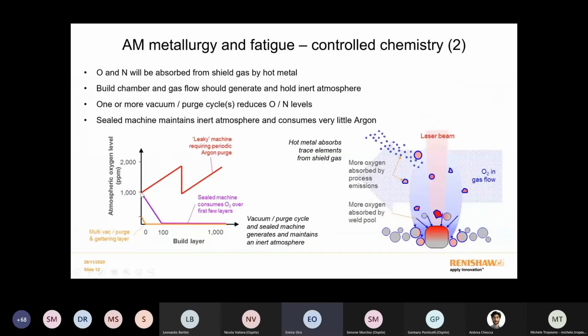Okay. This behavior, this red line, is a machine that is not behaving properly, so it continues to leak argon, and you have to purge the machine regularly, and you still have an unwanted concentration of oxygen inside the inner chamber. This behavior is a good machine: once you have an initial purge phase, and then maybe in the first 100 layers, absorption of oxygen by the metallic parts that are melting over the plate will keep a low oxygen content throughout the build. This is what we're aiming for and what our machines are designed to do.